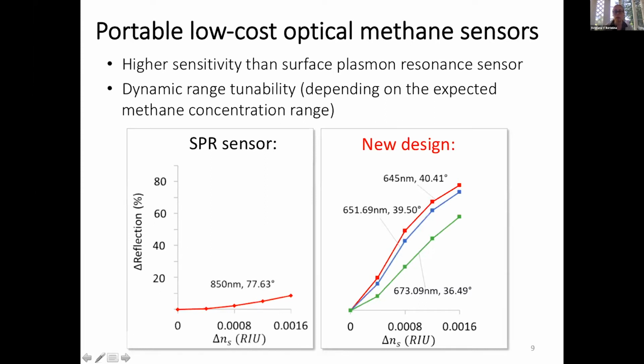And what is more important, we can calibrate it by very simple changes in the sensor itself or in the interrogation mechanism, just simply changing the angle, for example. We can tune it to a desired concentration, because sometimes you have a situation where you know that the concentration range is going to be very narrow, then you want to have a very sensitive sensor, very high slope. But in other situations, we know it's a more broad range. So if we make our sensor too sensitive, it will actually become saturated after some measurements, and then you cannot see anymore. You cannot quantify what that concentration is.